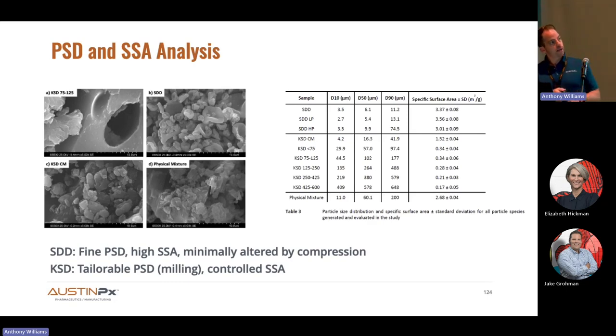With spray drying, you see much finer particle size, as you might expect, and a very high specific surface area that's about an order of magnitude greater than the KinetiSol particles. Even when we go to the extreme of cryomilling the KinetiSol material to reduce the particle size to a minimum, we're still only about half the specific surface area of spray drying.